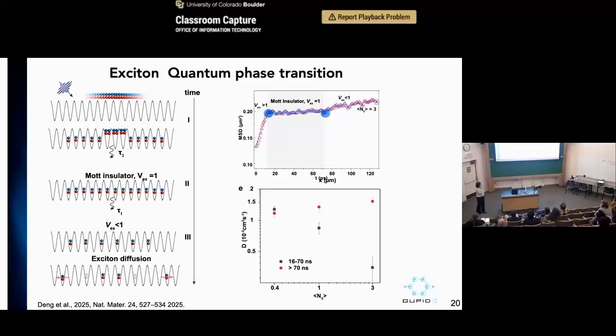So I'm just going to summarize what kind of phases we see in this measurement. If we look at the MSD as a function of time, you see these 3 different time regimes. Initially, it changes very fast, so everything's moving very fast. That's because initially we create a very dense exciton cloud in the middle, and they are so dense that they have strong interaction between them, so they kind of float above the Moiré lattice, so they're expanding very quickly. And then they will find on the edge some empty site to go into.